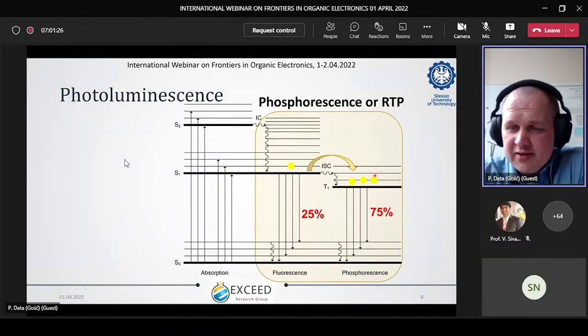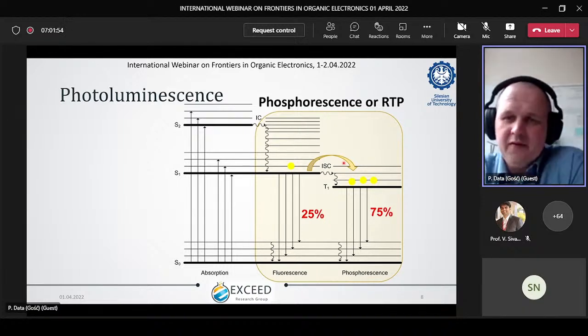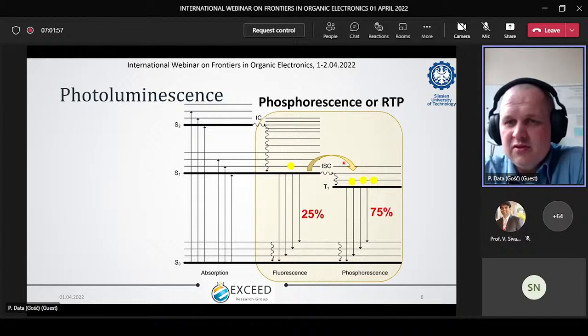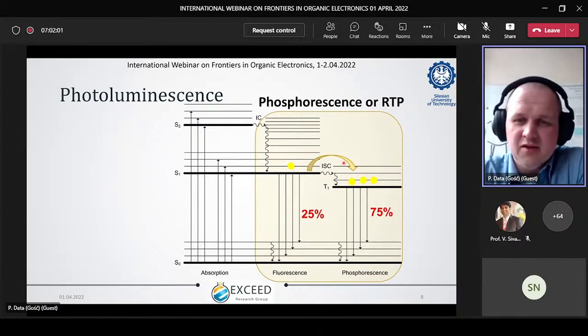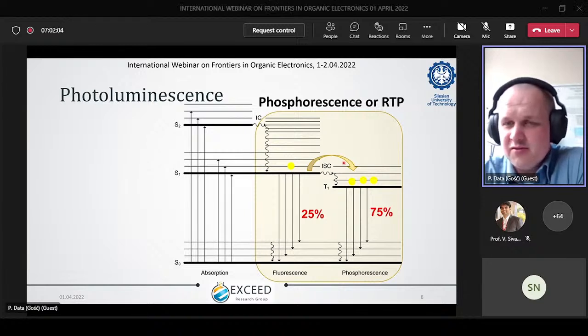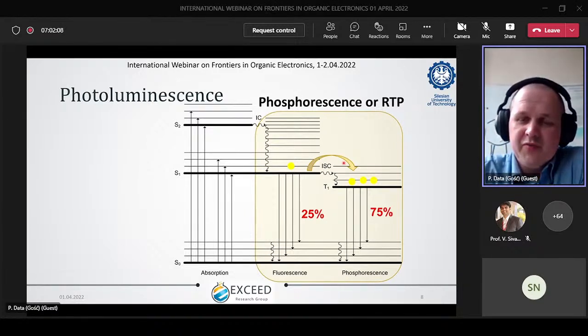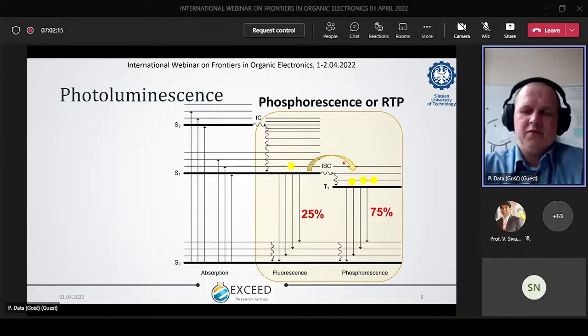Nevertheless, in the organometallic complexes, thanks to this metal ligand charge transfer process, this process is much faster. So where typically phosphorescence can have millisecond or even second lifetimes, in the organometallic phosphorescence emitters, the lifetime drops to microsecond time. And that's important for application in OLEDs, especially if you think about your mobile phones, AMOLED screens. If you have a lifetime in the milliseconds or in the seconds, you will need to wait until your face or your video unfreezes on your screen, and we don't want that. So our emission should be very fast. And for that, phosphorescence emitters, metal organic emitters were quite fruitful.